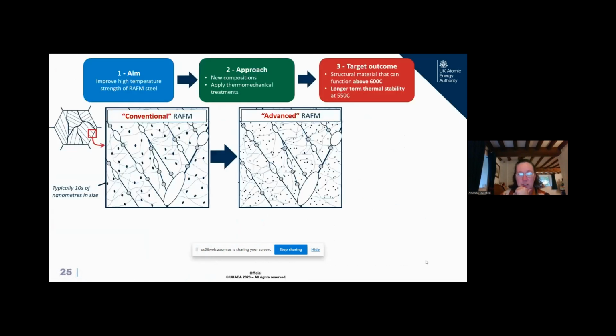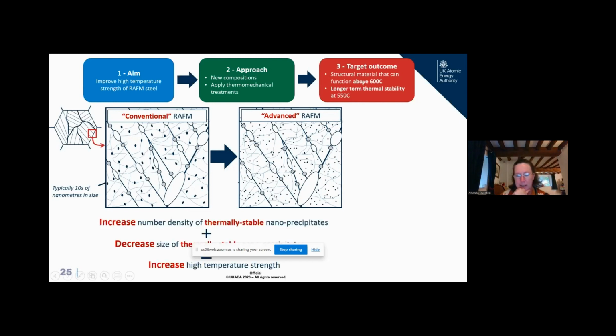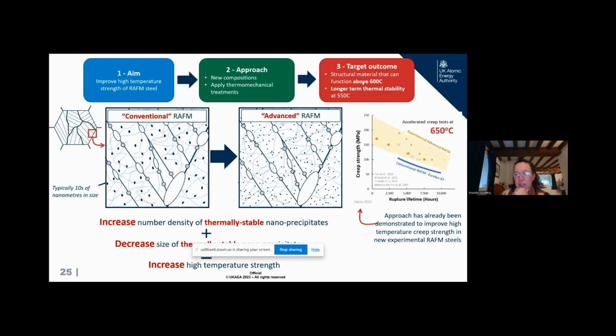So what we've tried to do is say, can we improve on a conventional RAFM with an advanced RAFM by applying new compositions and improved thermomechanical treatments and get ourselves to something of higher temperature? Can we increase the number of precipitates, decrease their size, increase their density, and see if we can get ourselves to something more optimal? And we do believe that we could get ourselves to 650. Both applying research in the RAFM area and the ODS area, and we have programs in both.